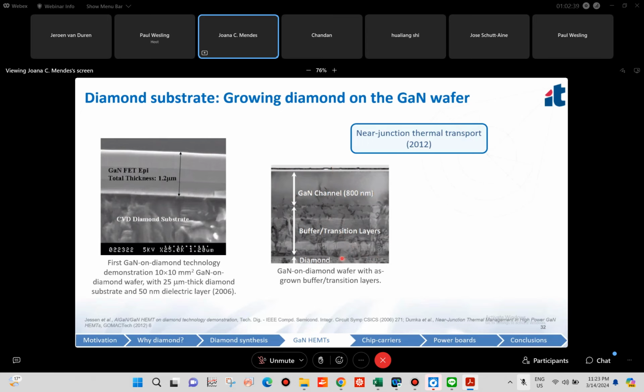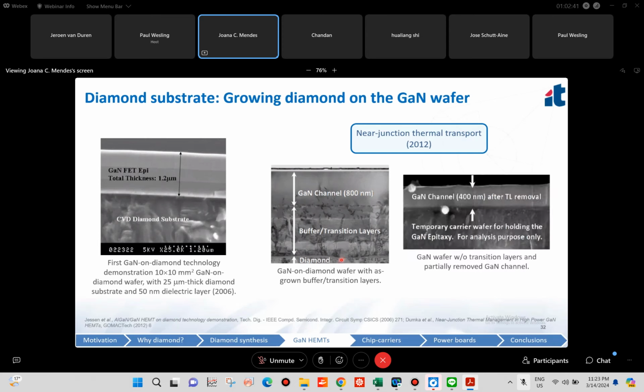diamond substrate. So what they've done is remove not only the silicon substrate, but also all these buffer and transition layers and also part of the channel. They were left with a 400 nanometer thick gallium nitride channel. That's where they grew the diamond.